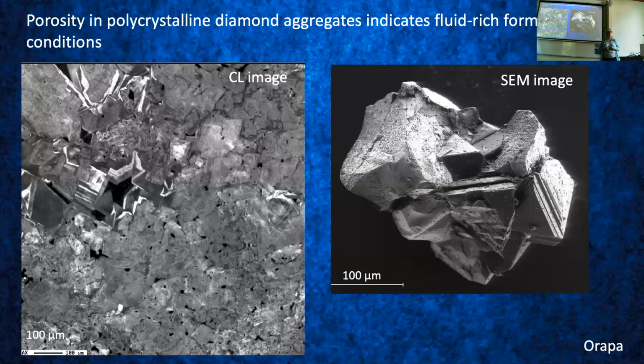As I said, different pulses, that's as far as we are with this, but we don't actually know yet how much time lies in between them. Part of this is because they're quite difficult to work with. It's diamond, you've got to polish that. It's not quite so straightforward. Diamond has this hardness anisotropy. Some crystallographic areas are much harder than others because they're polycrystalline. It's a random assortment, so you always get stuck with this hardness anisotropy. So it's hard to polish.